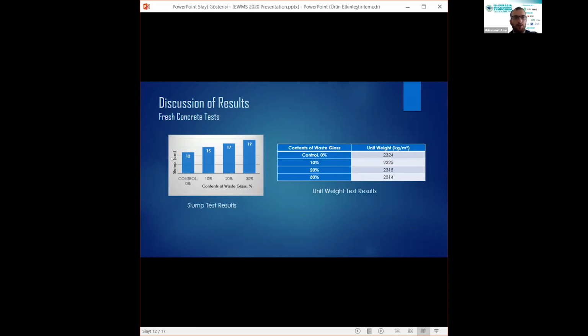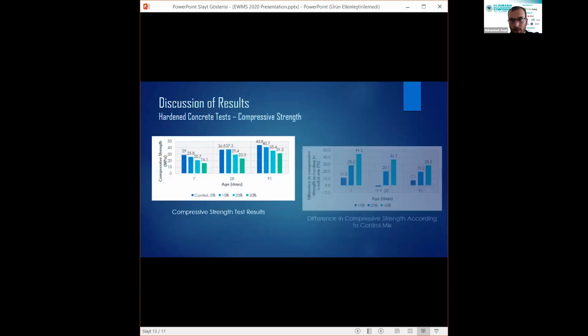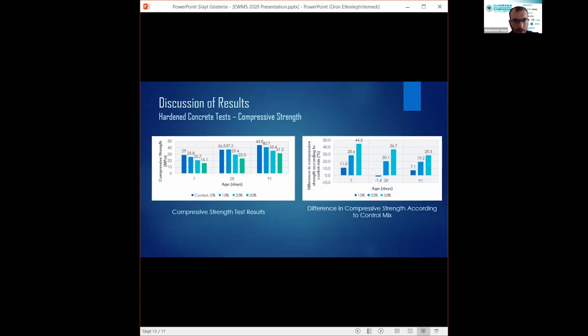The results showed that the slump increases significantly as a function of cement replacement ratio by the waste glass powder. Compared to the control sample, slump increased by 22. I am passing this part because I have to be fast. And the unit weight of fresh concrete is given in the table. Although the unit weight values are close to each other, it has been observed that the unit weight decreases as the amount of the waste glass increases.